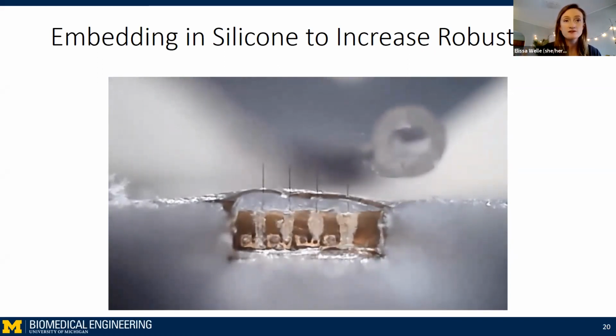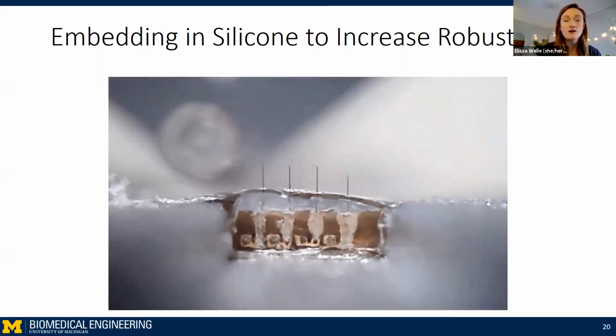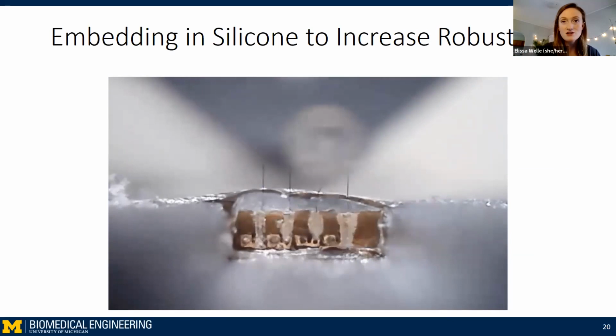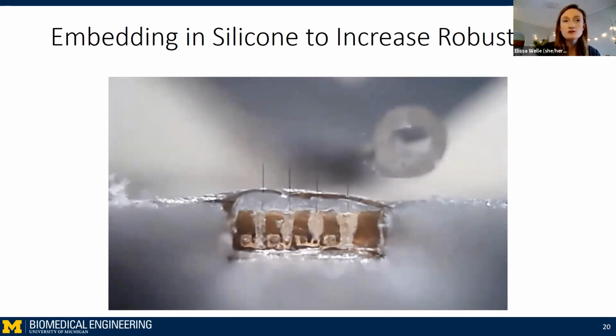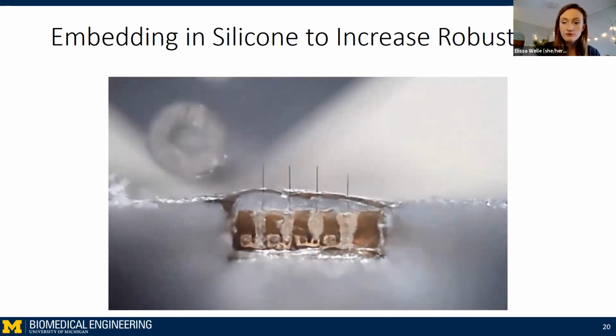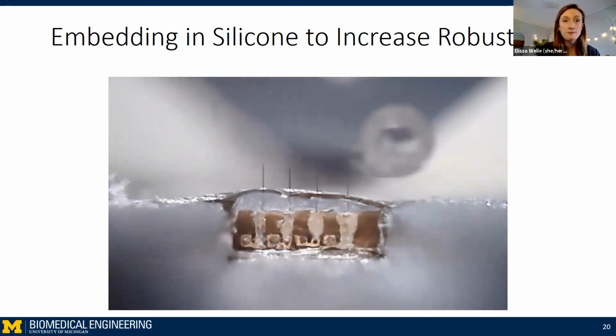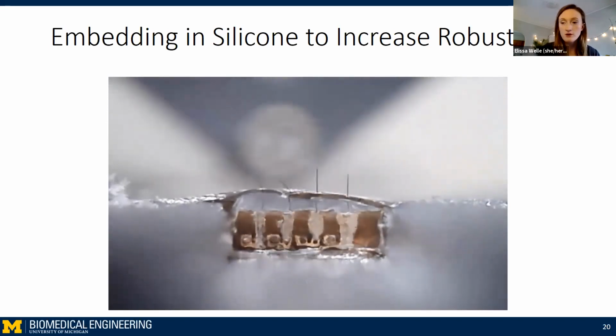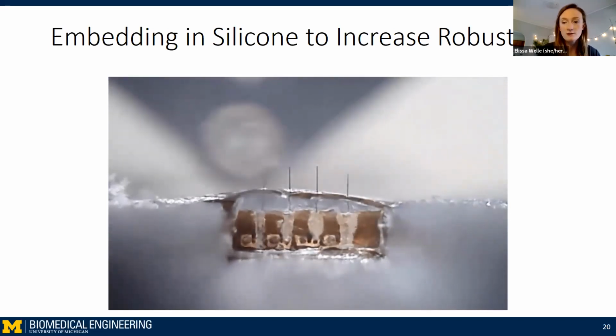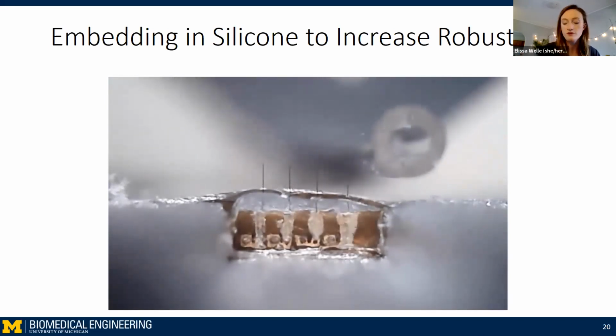We went up to 50,000 cycles. There was no breakage at that. We stopped then because there's no breakage. But this shows the good fatigue resistance qualities of the carbon fibers I mentioned before. And this is something that is very useful when talking about chronically implanting these devices in peripheral structures where there's lots of movement within the body.